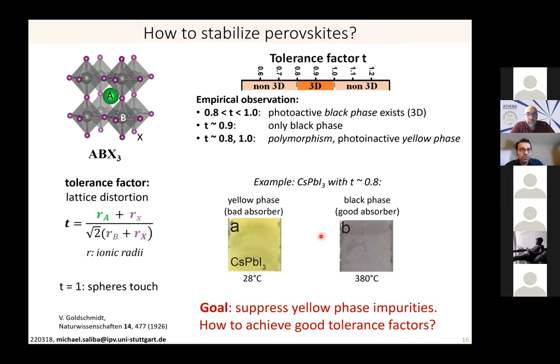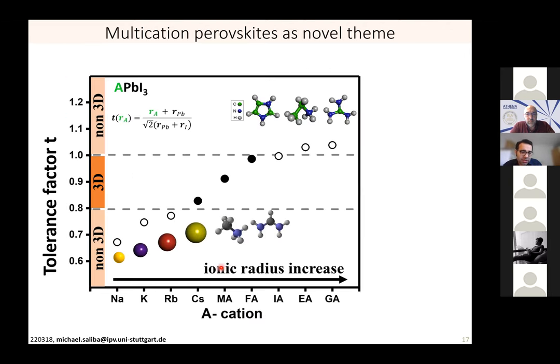So then the goal for us, and the bigger question, is how can we use this tolerance factor to get an idea of what is a stable and what isn't a stable material. And in this graph here, it's a function of the tolerance factor over the ionic radii. The lead iodide position is fixed, so the second and the third position, because this gives the most redshifted possible band gap, which is beneficial for solar cells.